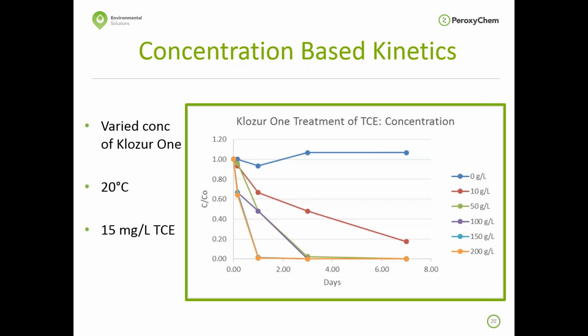The same was observed using TCE as a probe. Somewhat interesting in that a number of these points fell relatively on top of each other, but you see the same general trend where with increasing concentration, you saw increasing rates of reaction. The 10 gram per liter system had just a little bit over 80% treatment within the 7 days, but you start getting into the 50 to 200 gram per liter concentration range, and you're seeing treatment within 1 day from 150 and 200 gram per liter systems, and then treatment within 3 days of the 50 and 100 gram per liter systems of 15 milligram per liter TCE. So basically, the quick summary of all this, of course, is with increasing concentrations, you see increasing rates of reaction of the contaminants.